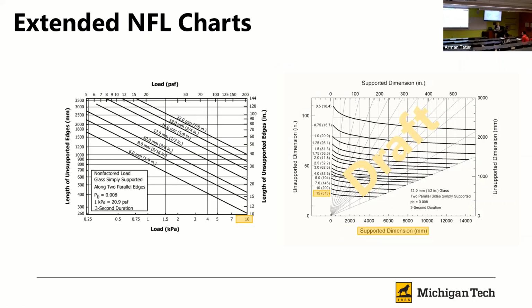The reality is if you have a plate supported on 2 ends and you have a uniform load, it is going to principally appear to behave like a beam, but you're also going to see it kind of fold in a little bit. In other words, we can see those unsupported edges rolling up some, okay, because of the way that plate action, the membrane action of the plate, is going to work. And so if we use that with our glass failure prediction model, we actually see that there's a little bit of a bend to these, okay, when we do that.